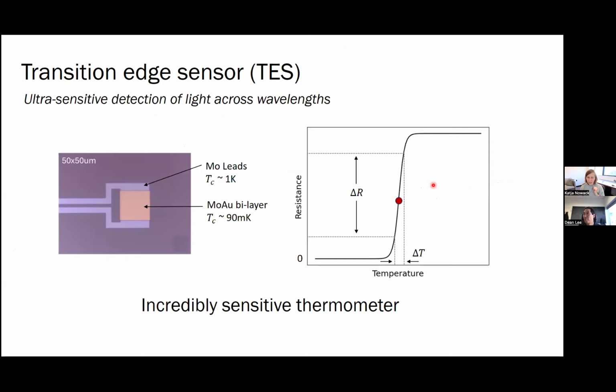I already told you a little bit about this, but there are so-called transition edge sensors that make use of that very sharp superconducting transition in a superconducting structure when you measure resistance as a function of temperature. If you position your system right on the transition, then what you're building is an incredibly sensitive thermometer. You keep monitoring the resistance. If your temperature changes by delta T, either it goes up a little or it goes down a little, you see a big change in the resistance. And that's how you build a thermometer.